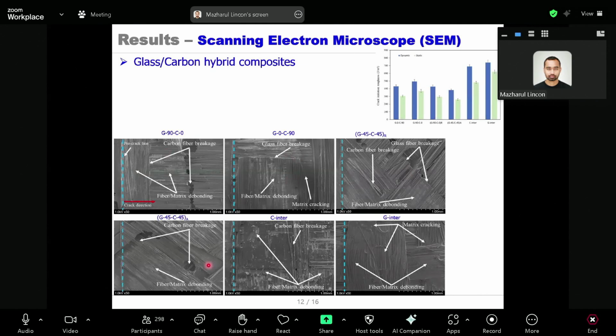Now, the other 2 composite types are G45, C45 repeating and alternating. In these 2 cases, the carbon yarn and glass yarn are at 45 degrees to the loading direction, and this layup is not an effective orientation to carry higher load. That's why with a smaller force, the carbon fiber or glass fiber breakage happens due to this ply orientation, and it shows less fracture toughness compared to the first 2 composite types.